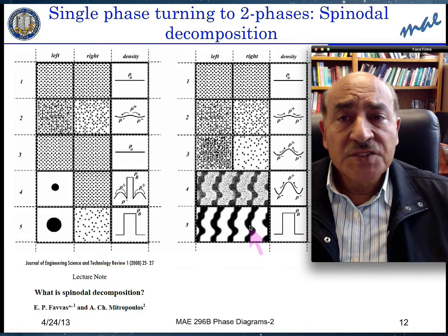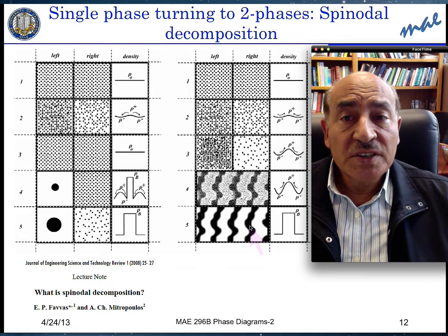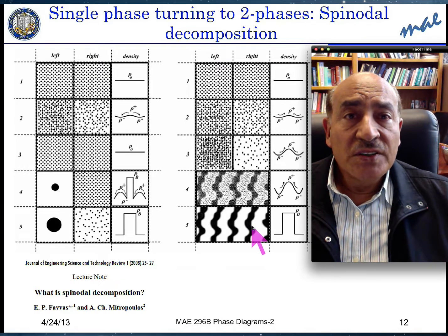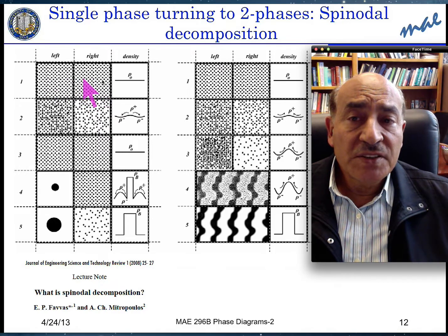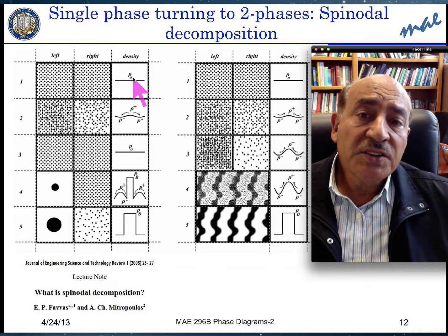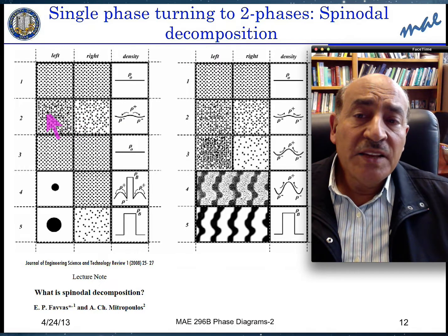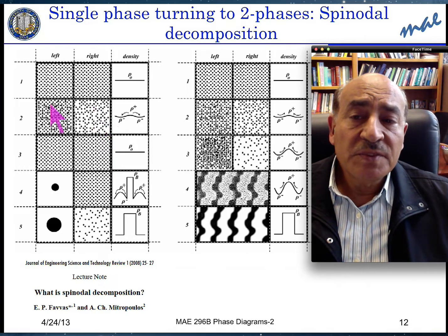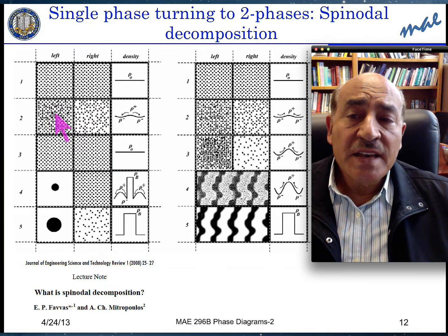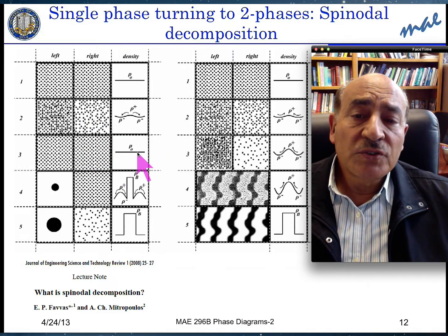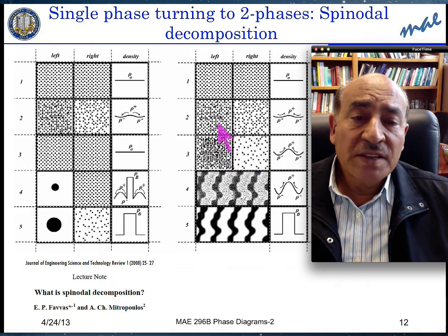This is to be contrasted with nucleation of a new phase, which is like a precipitation reaction. So in a nucleation, we have the two regions in space here, the same concentration, and then you have a fluctuation. This guy lost a little bit to this guy. Then nature is going to push that back in here because it's the same, so it goes back to here and you get uniform concentration. So this is for small fluctuations, unlike the small fluctuations here.